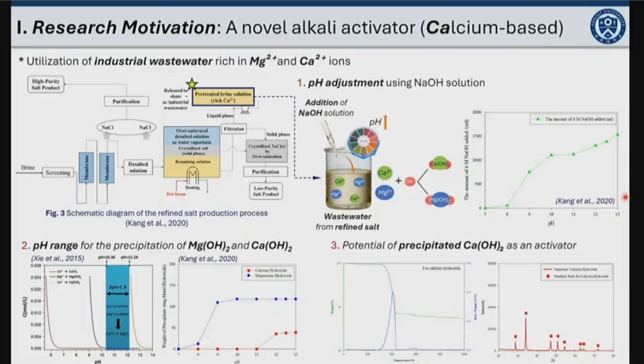Such new activators can be obtained as byproduct from seawater-based industrial processes. For instance, wastewater rich in magnesium and calcium ions, generated from refined salt production, can be utilized. In the first step, the pH of the wastewater is adjusted using sodium hydroxide. As the pH increases, the magnesium and calcium ions in the wastewater react with hydroxide ions, precipitating as calcium hydroxide and magnesium hydroxide. As shown here, the calcium hydroxide typically begins to precipitate at pH levels above 11. In addition, the XRD and TG analysis confirm that the resulting byproduct is the crystalline calcium hydroxide.